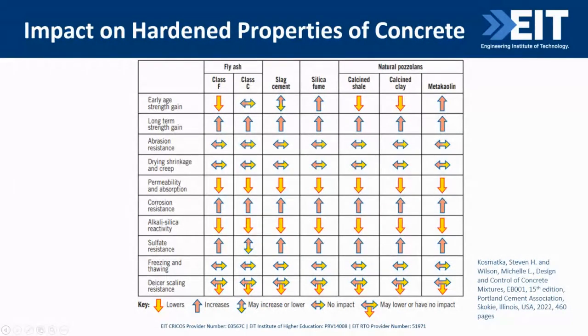Okay, supplementary cementitious materials can modify the microstructure of the hydrated matrix quite significantly. The increased fraction of calcium silicate hydrate (CSH) leads to a more homogeneous microstructure, particularly when highly reactive, finely divided supplementary cementitious materials are used. Adding supplementary cementitious materials will reduce the overall porosity and the pore sizes of the hardened concrete.